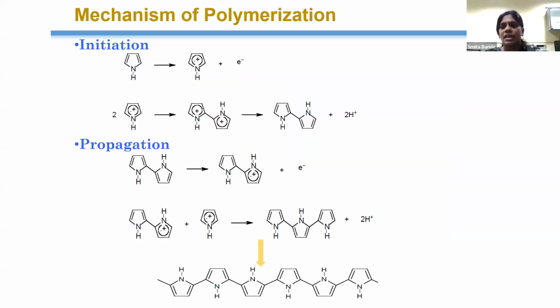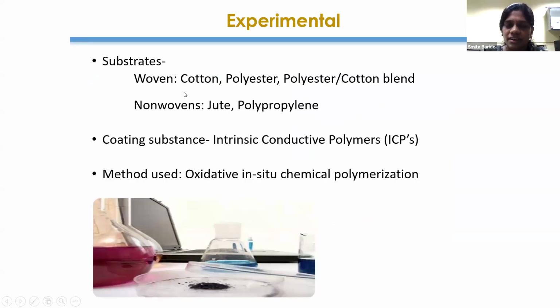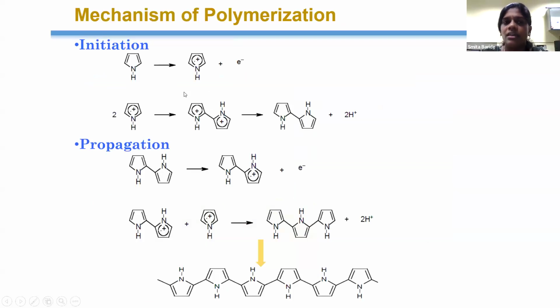So if we see the mechanism of polypyrrole formation, for example, here the monomer is a pyrrole. In chemical polymerization, the reaction basically takes place through an oxidative force that is applied to the monomer. In this case, our monomer is a pyrrole. When we add an oxidizing agent to it, an initiation process takes place, and there is a formation of radical cation.